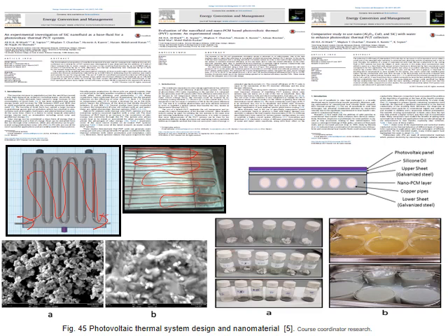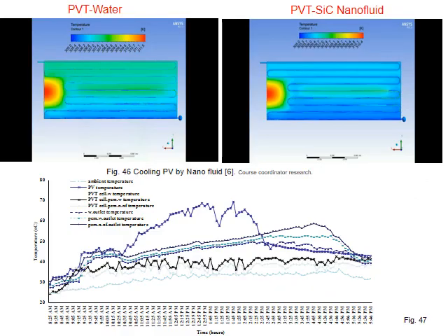We need to do some tests on these PCM to make sure that they are mixed correctly, their properties, what they are, viscosity, density, and so on, and different percentages of nanoparticles used. Here you can see different percentages, and when we mix it, the color, you can see it is changed. And we try to take an XRD test to see the homogeneity of the nanoparticles within the PCM and within the nanofluid.